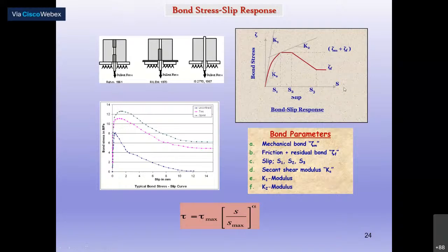We would not have come across this, but these are the things required. Some softwares take this information also to understand the bond in the reinforcement bar with the surrounding concrete, and the reinforcement characteristics and concrete characteristics, model every phase involved, and then all realistic material characteristics are incorporated. Then when you use this software, you can come out with the solution exactly agreeable with the experimental finding. That's what you have to do. Unless you have some planning, unless you have accuracy in the system, whatever may be done in the computer, you'll get some result, but that result cannot be acceptable. So you have to validate with the true experimental findings, and again, the efficient software should be developed.